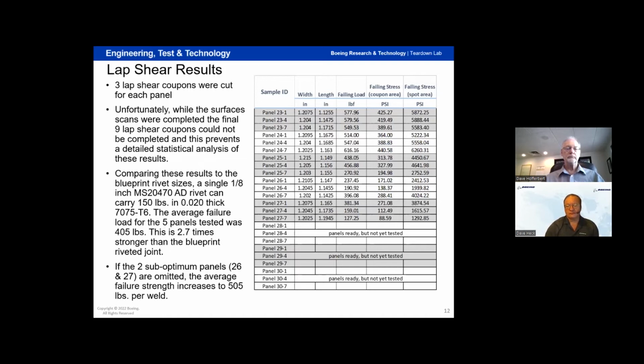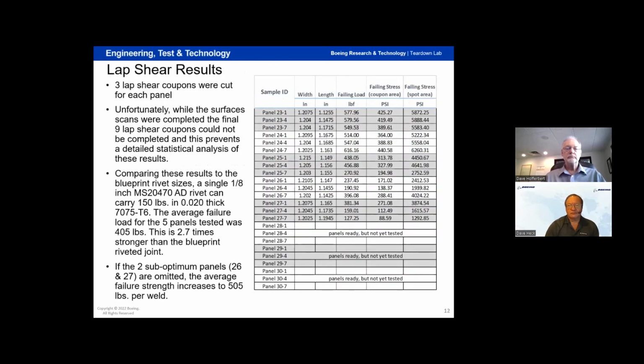So quite a bit of a jump in the shear strength of these. And these are material to material, no rivet head there to help you, no actual rivet there. So we were able to get some pretty good strength out of this process. But we weren't able to get the fatigue or the lap shear testing completed for the statistical analysis.